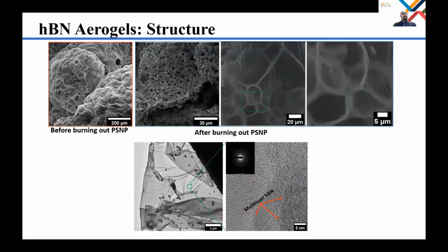Low magnification TEM image shows us a large folded BN sheet with small BN particles on the surface. And high resolution TEM image and diffraction pattern show that the BN structure is polycrystalline. And here the dark regions, which are marked with arrows, show multi-layer BN sheets.